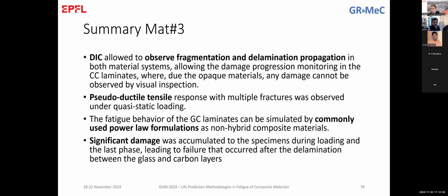Of course, again, this is a validation of what we've seen until now. We checked 3-4 different materials, and always the typical power law formulation for the SN curve is valid. This is the formulation that was introduced more than 100 years ago. So the methods are practically available for any material system regarding the power law formulations for fatigue, and regarding the Weibull distribution for all the data, even strength data, stiffness data, they all follow more or less a Weibull distribution.